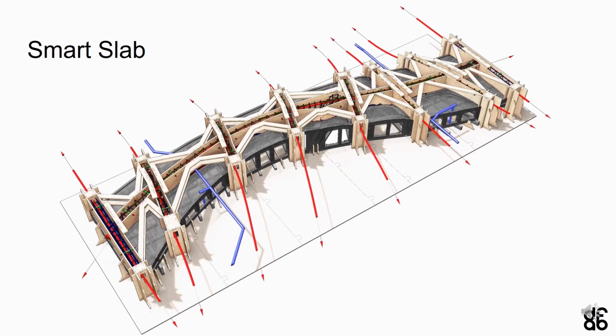For example, for the Smart Slab, the soffit was defined by the 3D printed binder jetted formwork, the upstand ribs by laser cut plywood sheets, the service voids by FDM 3D printed formwork, and moreover, two different concreting processes with distinct mixes were used, casting and spraying, and finally, 3 types of reinforcement were used: fibers, rigid bars, and post-tensioning. All these different processes have their own supply chains that are difficult to manage and are liabilities for contractors.